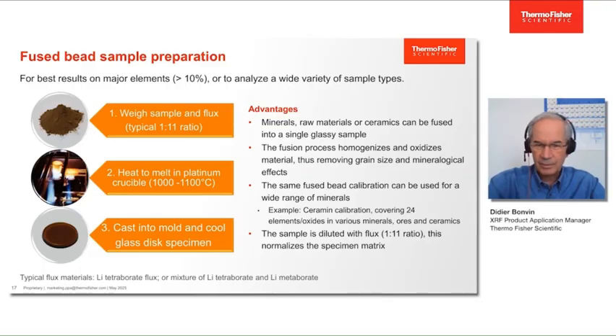One of the disadvantages, of course, is that we are going to dilute the sample. Typical ratio is one part sample and 11 parts flux. The flux being a mixture of lithium tetraborate and lithium metaborate, typically. And this dilution means that the limits of detection for trace elements will not be as good as we get when we just press the sample as previously presented.